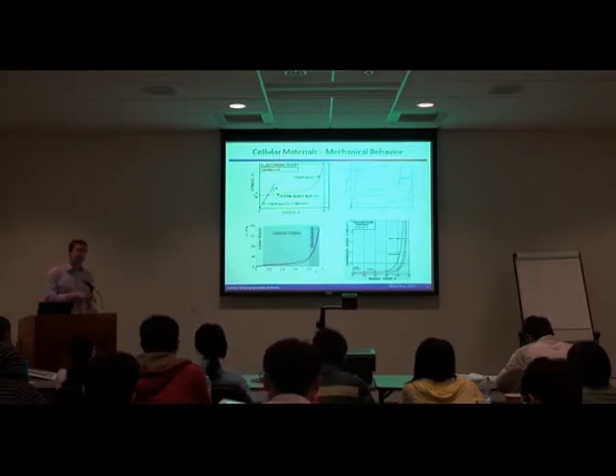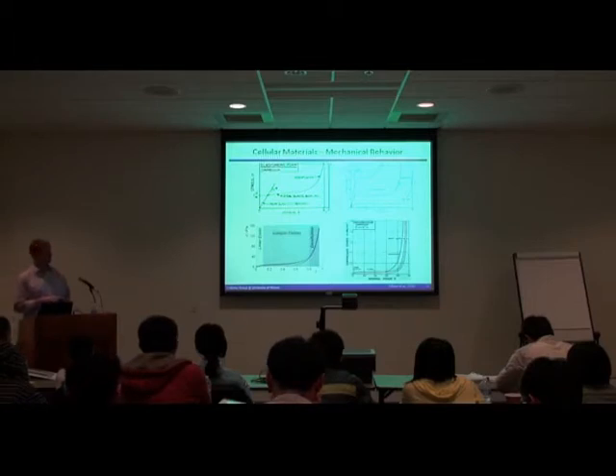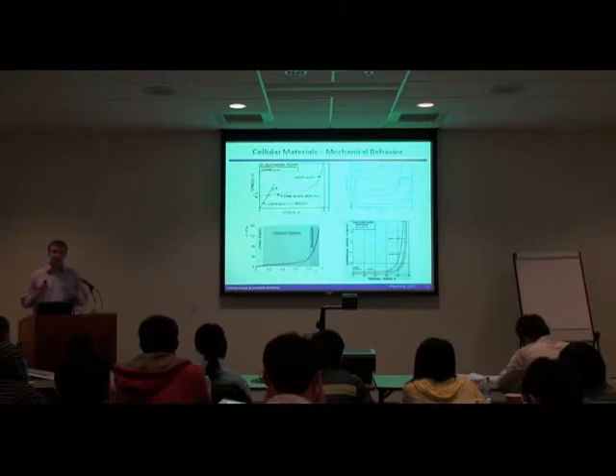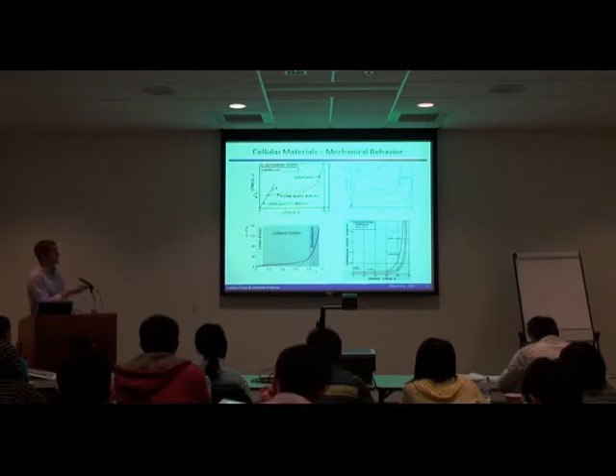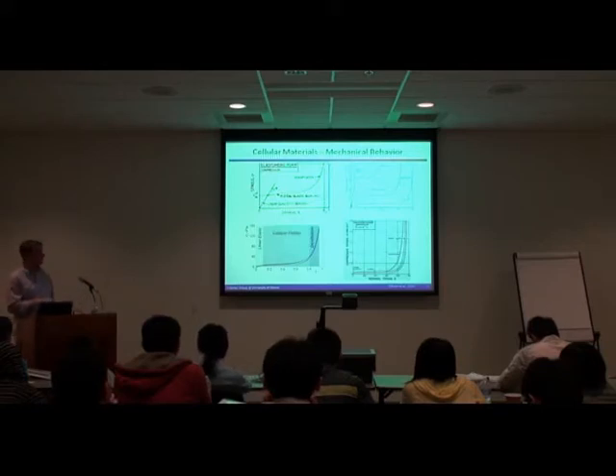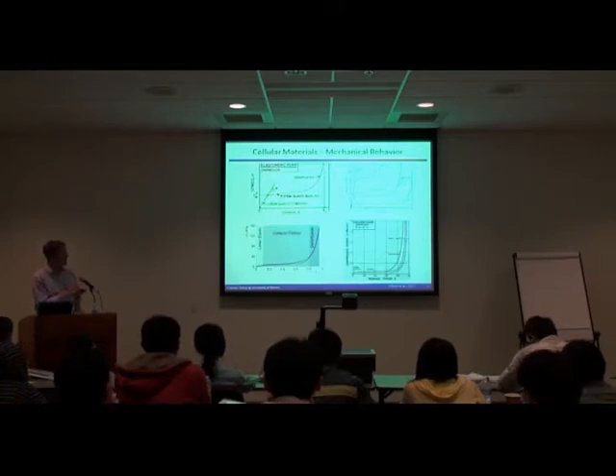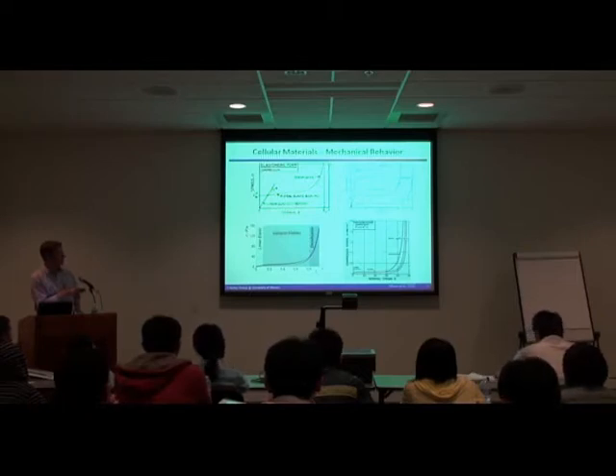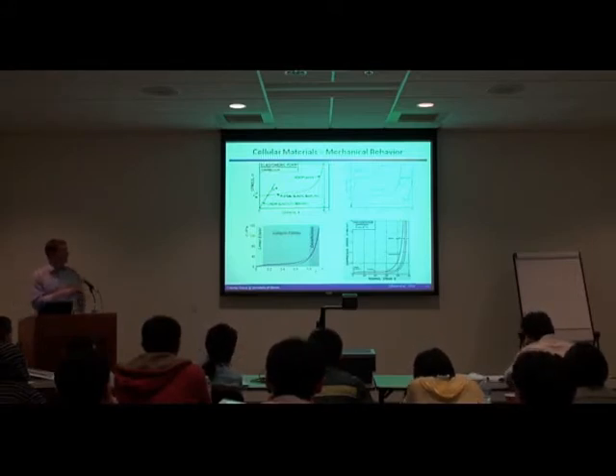These materials can be compressed down to 95+% strain because they're low density in nature. This elastic buckling plateau is associated with all the fibers within the material starting to buckle and collapse on top of themselves. And then you get a densification event that occurs when the fibers are compressed on top of themselves, and then you're actually compressing fibers on top of fibers. And so this is sort of a generalized one to look at what you might expect to see for the generic low density open cell foams. We've seen this behave quite well for a whole host of different structural materials. These are elastoplastic materials that are low density open cell foams. Depending on the density, you get different behaviors, but fundamentally, the behavior is somewhat similar.